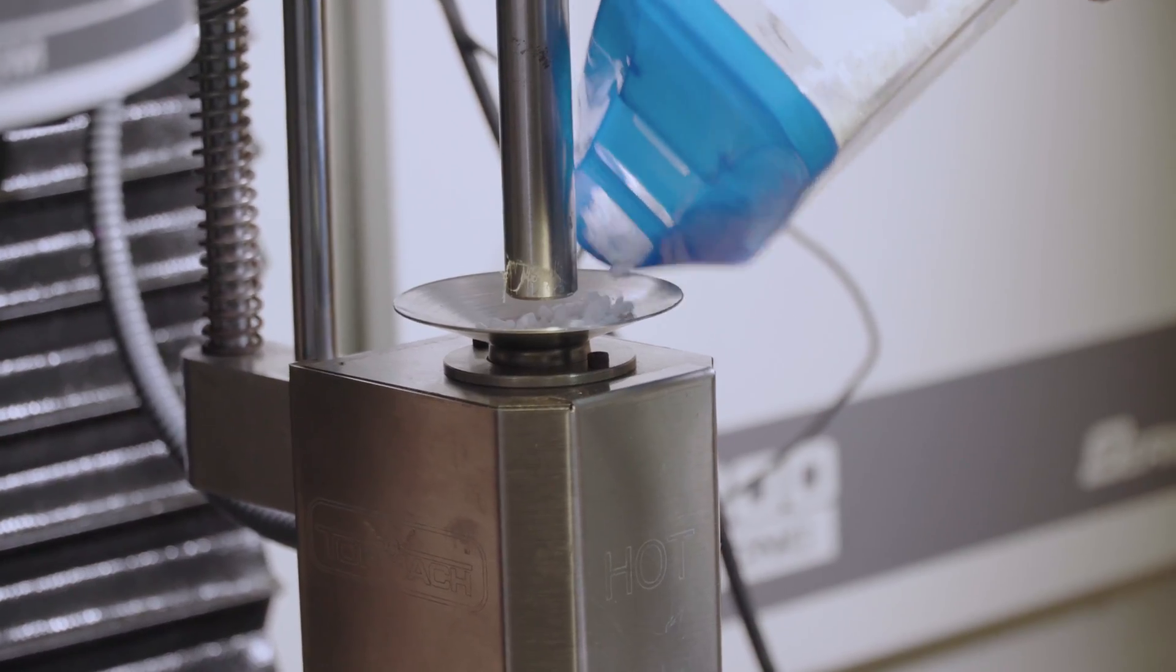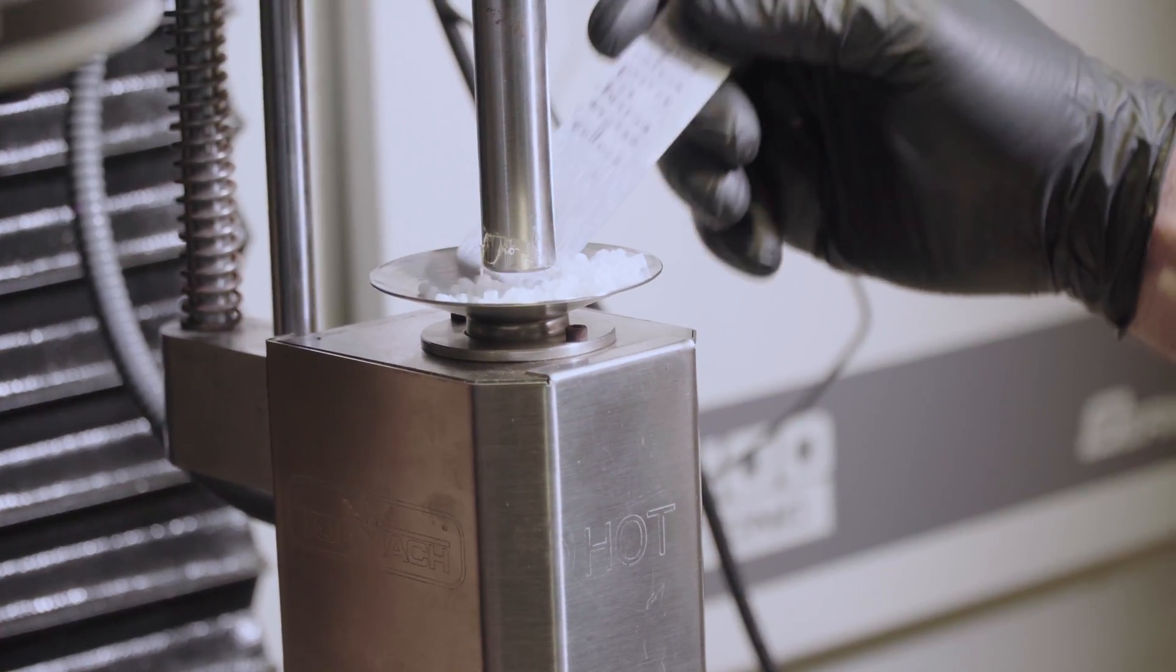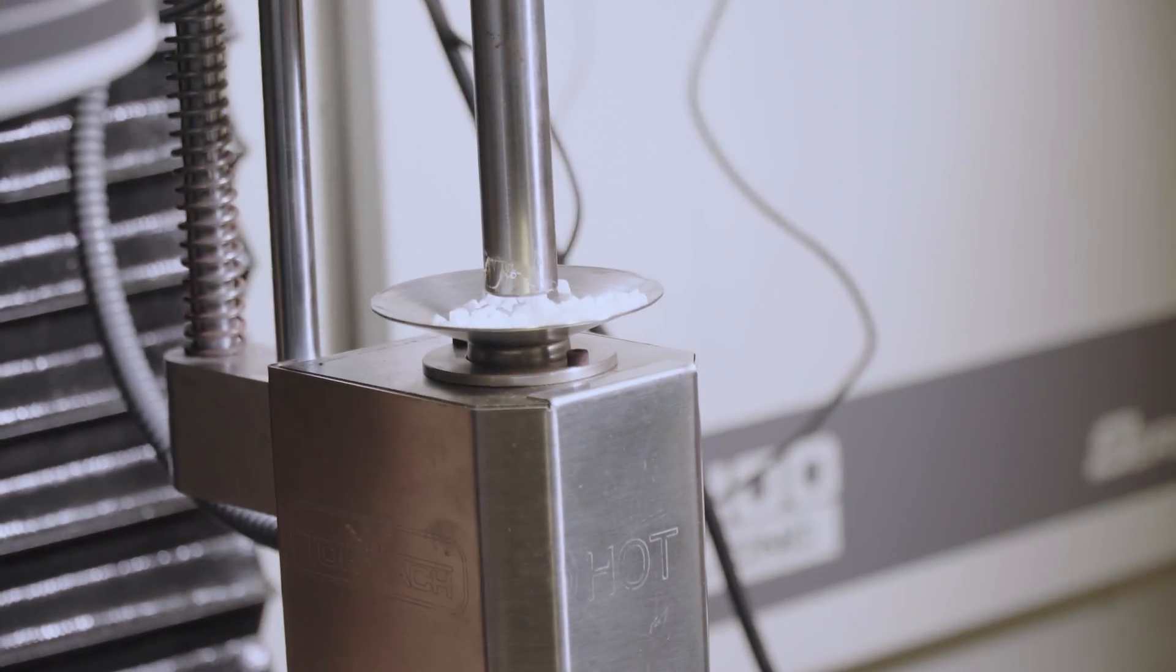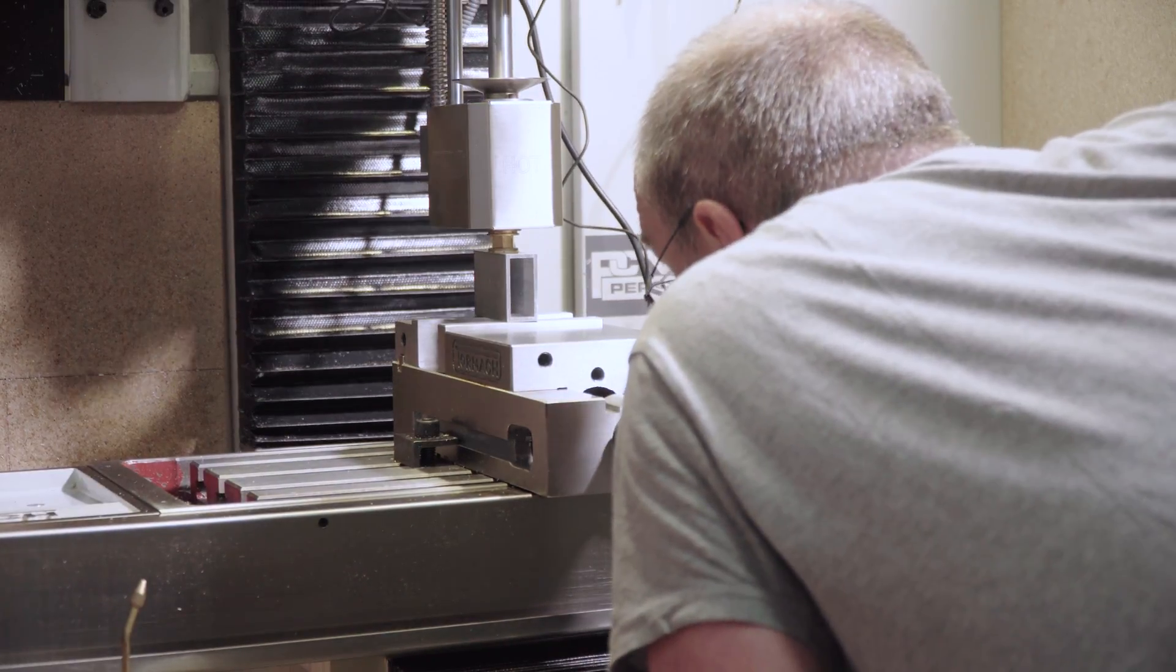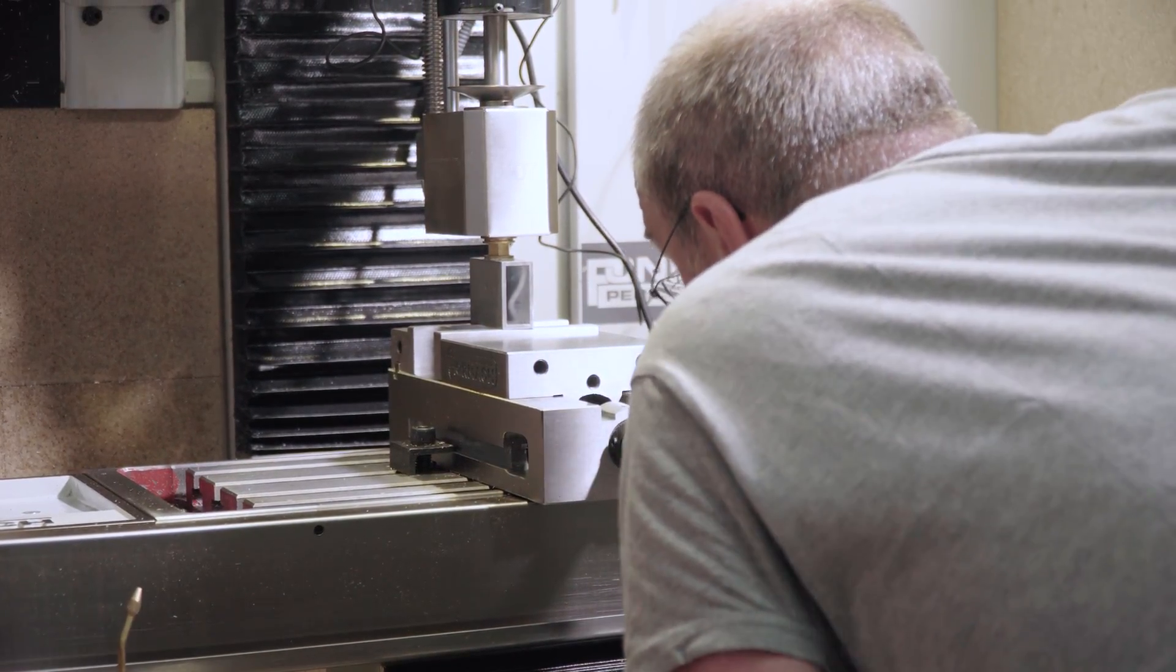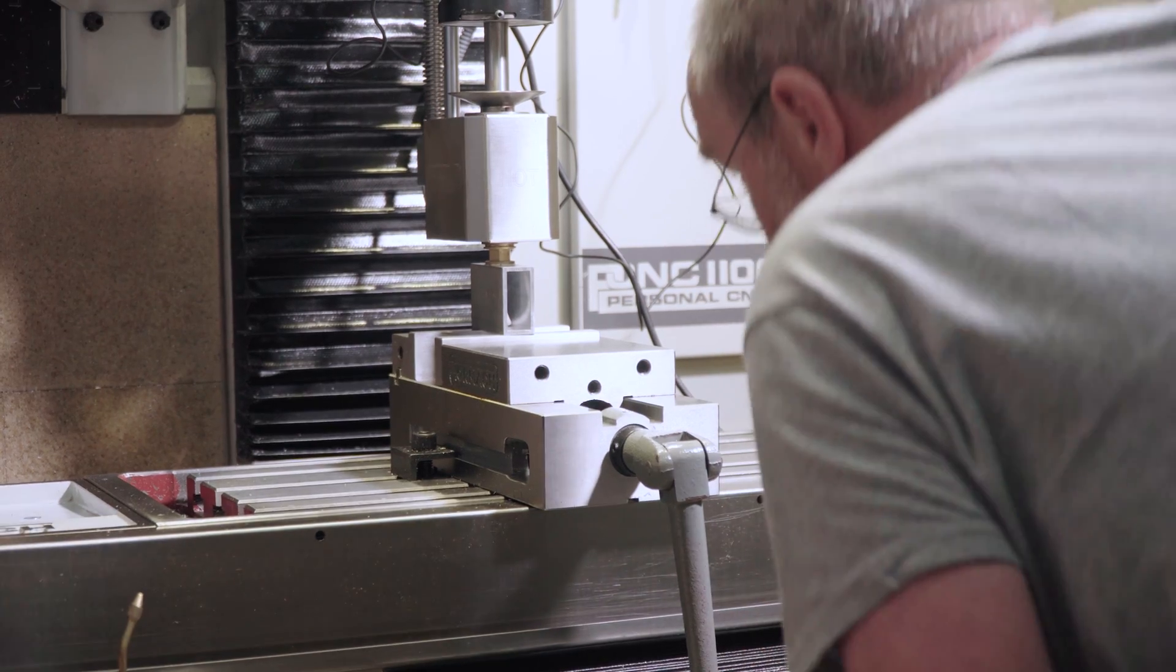So we're putting in the raw plastic at the top. Then this ring gets heated up to the 240 degrees, when we tried it then with 260 degrees. The ram of the CNC mill goes through this cylinder and stamps. Basically the liquid plastic pushes it into the form below.